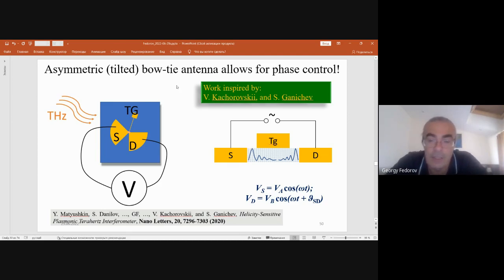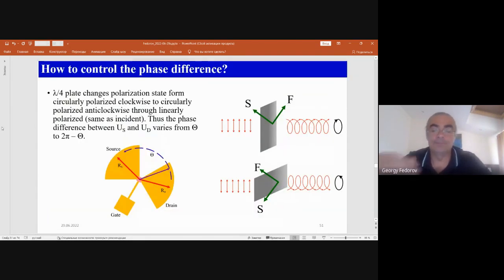So this work was inspired by Valentin Kachorovskii from the Ioffe Institute and Sergey Ganichev from the Terahertz Center in Regensburg. And the idea is that we want to control the phase of plasmonic waves excited by different sides of the graphene channel. And in order to do this, we can do it easily. We do it in two steps. First, we bend the dipole antenna, make it less symmetric. And the second step is that we can start playing with the polarization of the radiation that falls on this antenna.